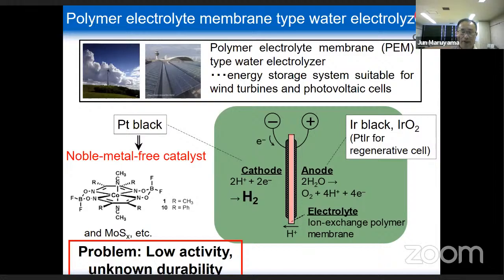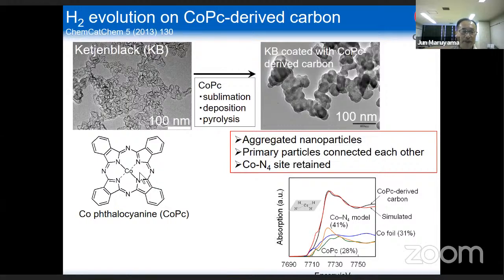The concept for making the catalyst is actually similar. The hydrogen evolution reaction can be catalyzed by a cobalt-containing catalyst. So I used cobalt phthalocyanine as raw material, and by sublimation, deposition, and pyrolysis of cobalt phthalocyanine, I could get this agglomerate-like, electron conductive, high surface area material that is active for hydrogen evolution.